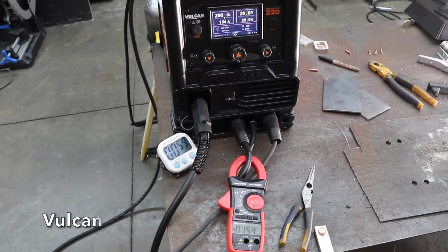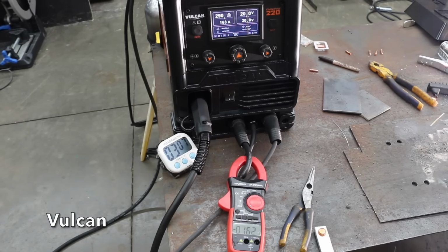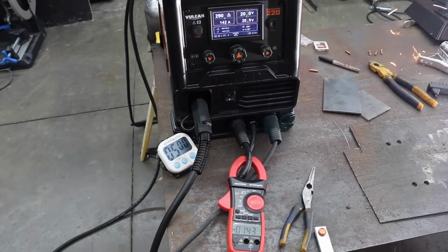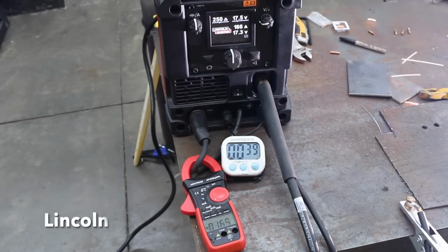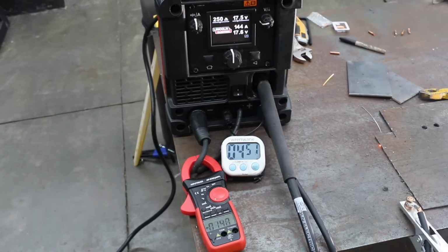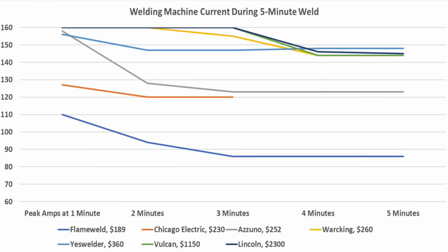And the Vulcan held on to 160 amps for the first 3 minutes and then dropped to 144 amps for the final 2 minutes. The Lincoln started off at 160 amps and then dropped a little to around 145 by 5 minutes. And this chart is pretty busy, but it shows just how closely matched the Yeswelder, Vulcan, and Lincoln are when it comes to delivering current for 5 minutes. The Warcking performed well, but it did shut down just before reaching 5 minutes.